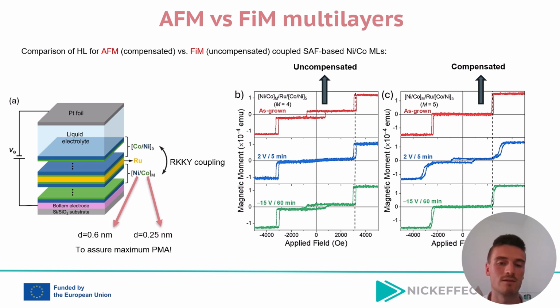The experimental setup shown in Figure A features multilayers separated by a ruthenium interlayer, which is responsible for inducing the RKKY coupling, as a consequence of the indirect spin change in direction between the bottom and top ferromagnetic layers.